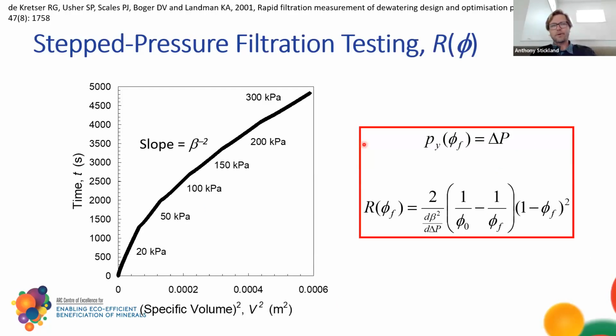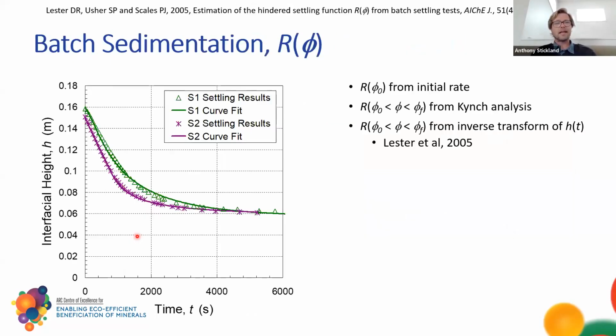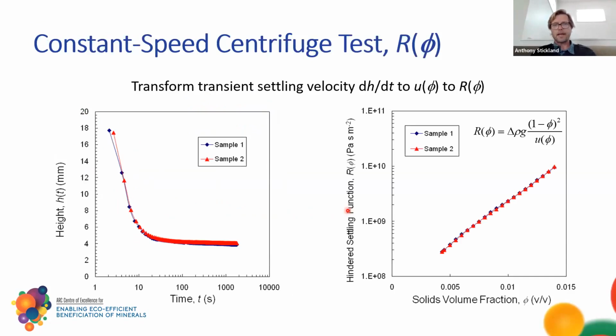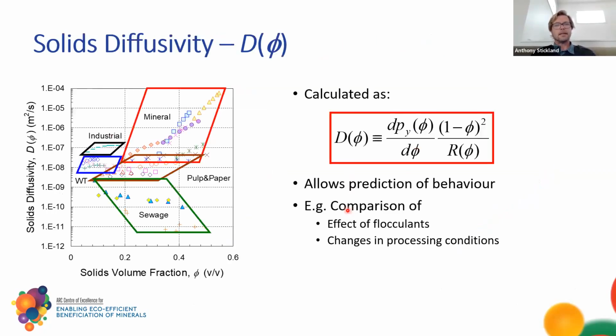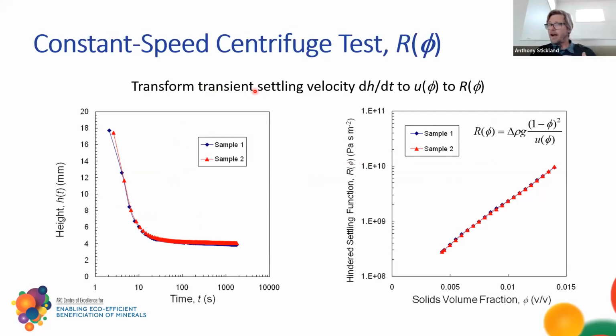I won't go through the explanation of all of these. We can get rate data from filtration testing. In this case, it's a stepped pressure rate test. So as soon as I've got enough constant slope data here, I step to the next pressure. We can get rate from batch sedimentation. So these are settling tests, and these are the analyzed results. So the analysis works fairly well. Same for the rate of settling in a centrifuge. So we can get Py(φ) and R(φ), these 2 parameters that explain the extent that I can go to and the rate at which it can come out.